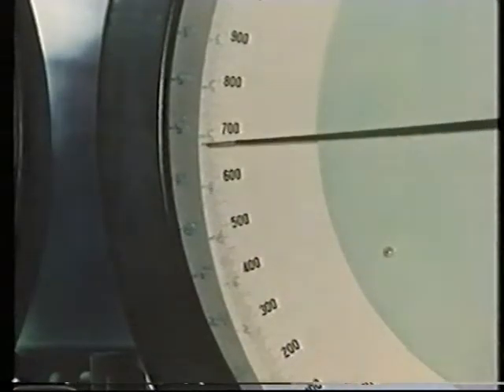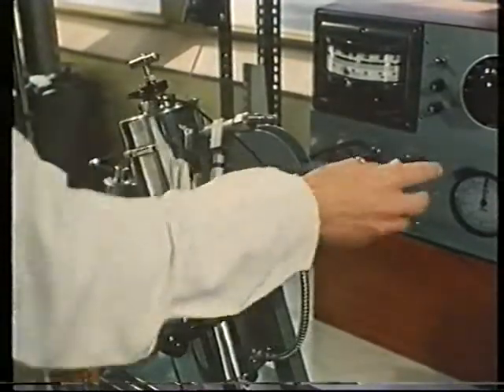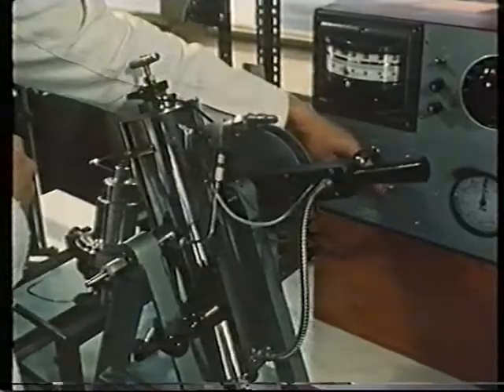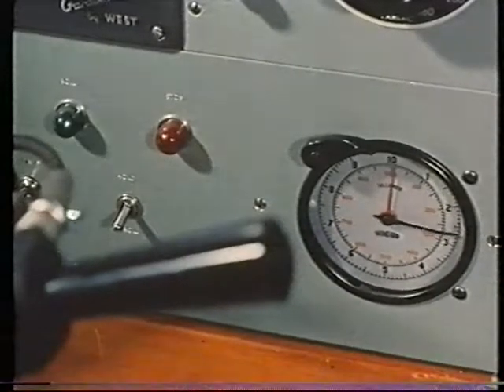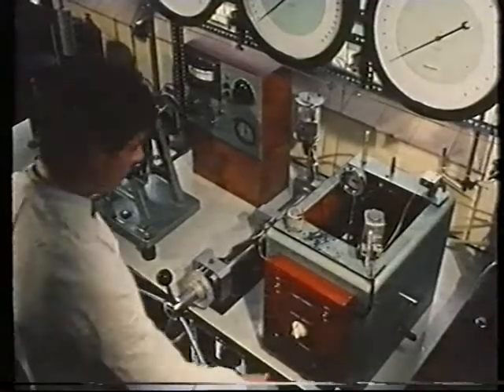Double the pressure to 700 atmospheres, and the oil becomes much thicker. In this instance, the increase in pressure has nearly doubled the viscosity of the oil. The ball now takes 14 seconds to fall. All oils are slightly compressible.